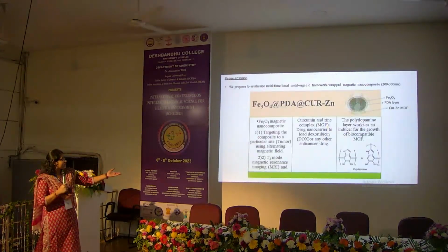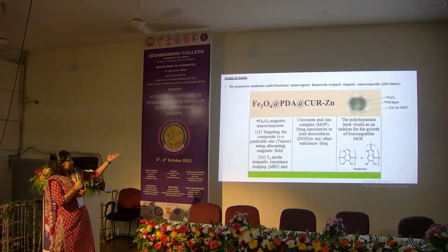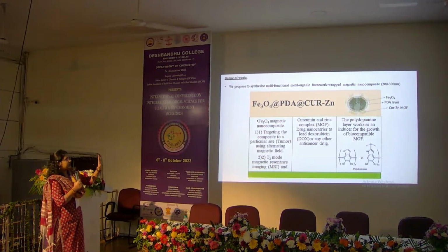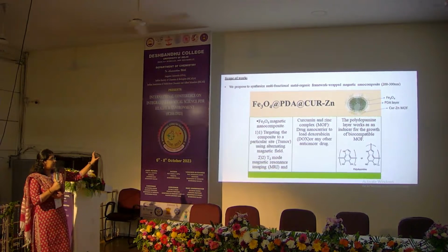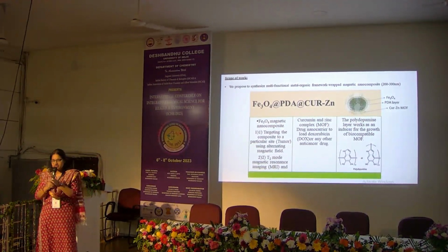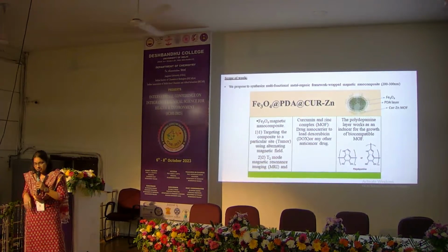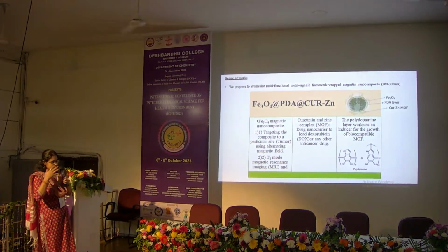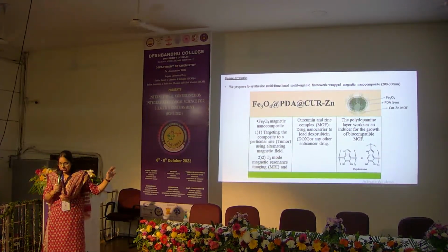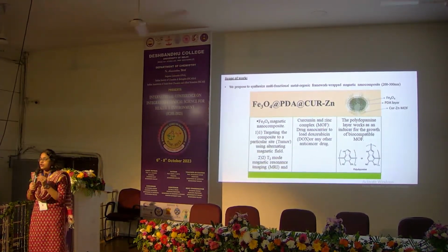Next one. My compound is iron oxide coated by PDA, that is polydopamine, and curcumin zinc. Here iron oxide is magnetic in nature, polydopamine is a universal coating agent and is highly bioavailable and biocompatible, and curcumin and zinc are used as a metal organic framework.